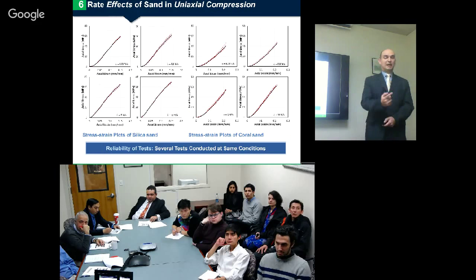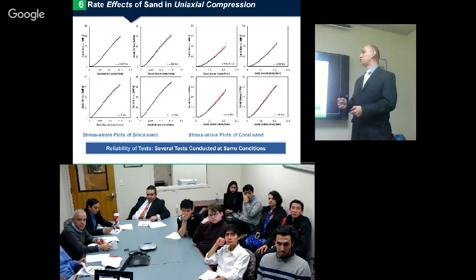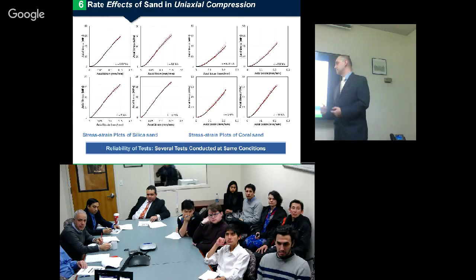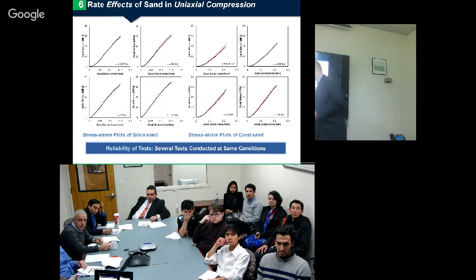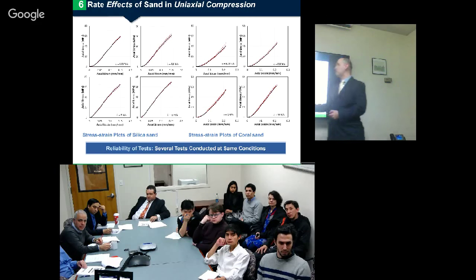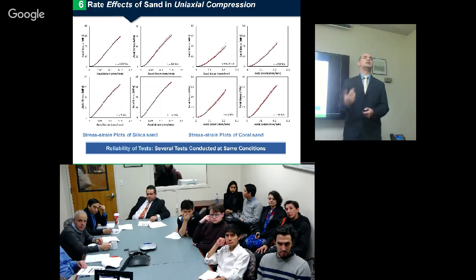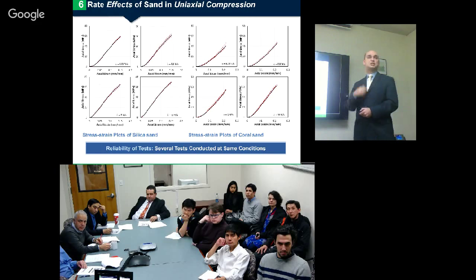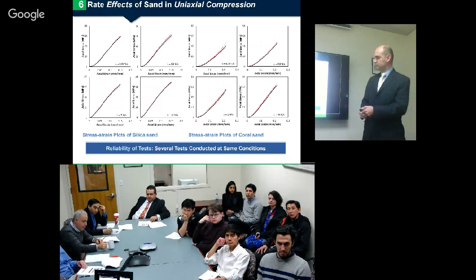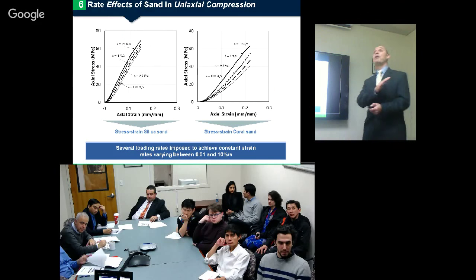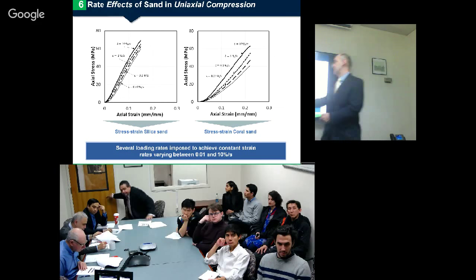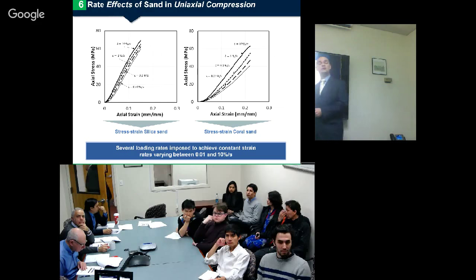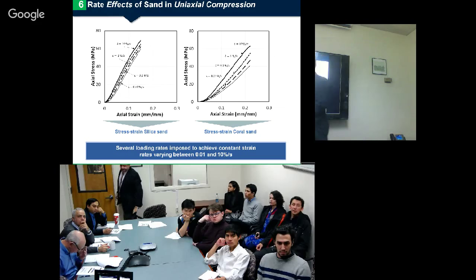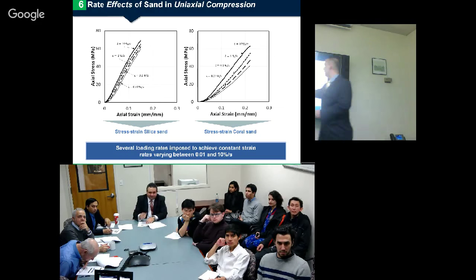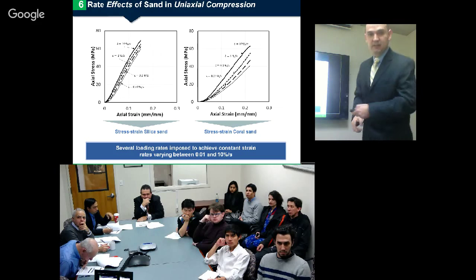So after these 4 tests per each condition, I was able to plot them together at different specific characteristics, such as for silica sand and for coral sand, we have 4 main strain rates, from 0.01 to 10% per second. The red dashed lines are experimental results, and the solid black line represents the mathematical average of them. But then at the end, we can plot the average of each one, and we can see that there is some sort of an increase on the stiffness and the final strength at the end. Here and also here, if you notice, the slope might be different.